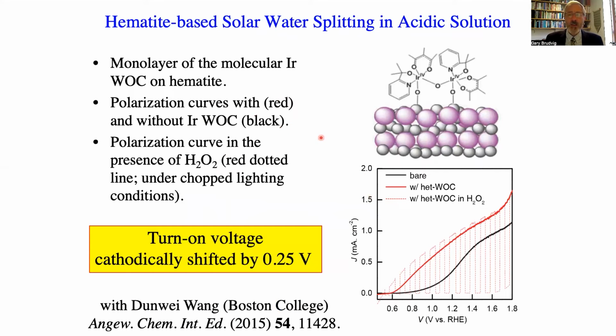We then use this catalyst in a variety of ways. One of them is to put it on the surface of hematite to improve the catalysis for water oxidation of hematite. And this is work we've done in collaboration with Dunwei Wang's group at Boston College. So we can put a monolayer of this molecular catalyst on hematite and examine the photocurrent as a function of applied voltage. And you can see that the molecular catalyst on the surface significantly improves the onset, cathodically shifting it by about 0.25 volts compared to just bare hematite.